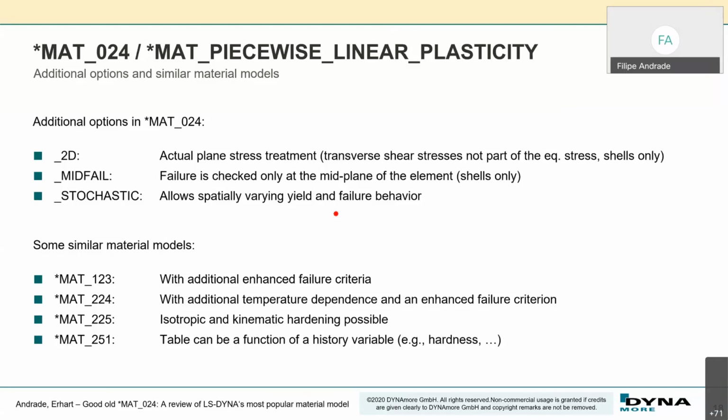Depending on your loading or load case or your application, you will see an effect or not. Another option is this mid-fail option. If you use that failure flag in LS DYNA, basically the failure flag is valid for all integration points of your element, which is not always a good idea. With this mid-fail option, you can enforce LS DYNA to check the failure only in the mid plane of the element.